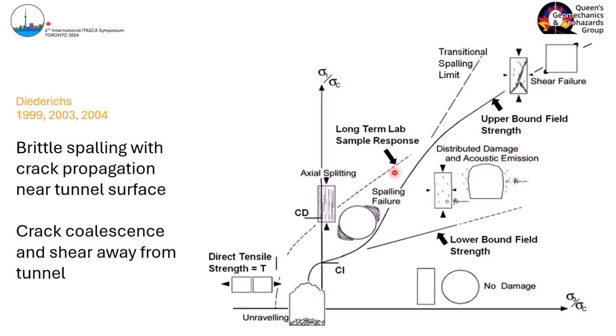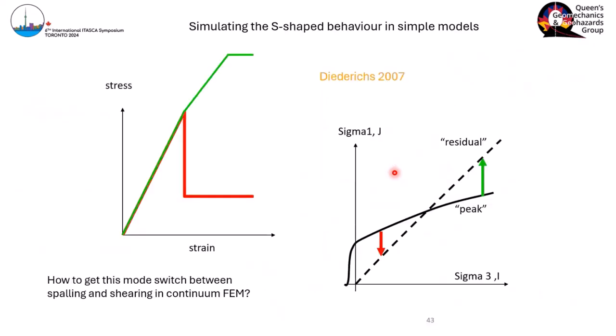This is the so-called S-shaped curve, which is now used fairly ubiquitously in rock mechanics, not necessarily as an S-shaped curve, because that's really hard. But we needed to go from here to find a way of putting this into a model. The first attempt for me was to fake it in RS2 finite elements. I had to get Brent Corkum to change the dialog box to let me put a higher friction angle for residual than peak, because they locked you out. This idea that you have a high cohesive, low friction peak, that's the fracture mechanics. And then when that yields, the cohesion is lost, but the confinement dependency increases dramatically.